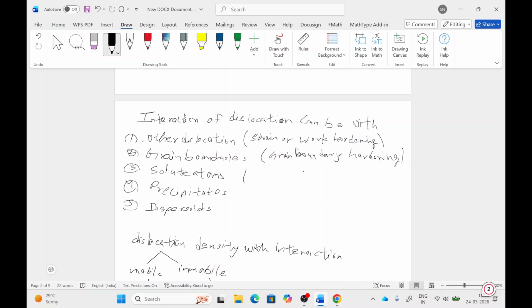From solute atoms, the elastic modulus difference and the atomic or crystal mismatch result in strengthening, so that is solid solution strengthening. With precipitates, it is precipitation strengthening, meaning the precipitate which forms with quenching of the material from high temperature and aging, so those precipitates also interact with dislocations. And from dispersoids, it will be dispersion strengthening.